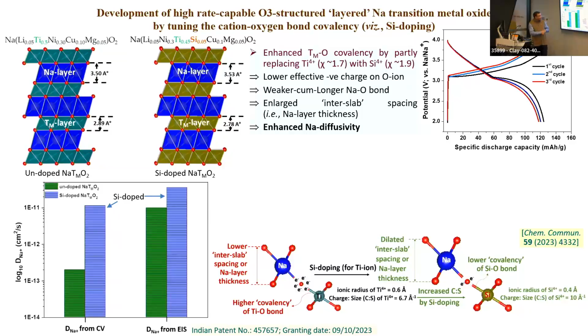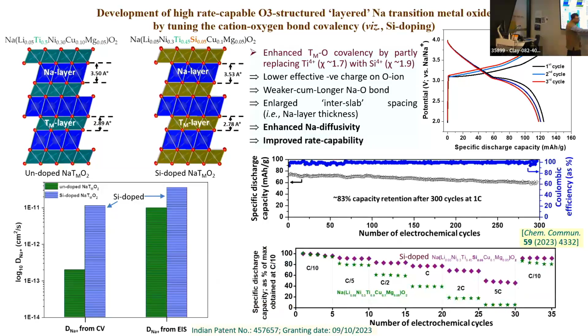So again, going back a little. Now this on the left hand side is the composition which was absolutely water stable, using which I had shown the aqueous process cathode. It was perfectly water stable. But then the rate capability was not that great, understandably. So we tweaked it a little bit. In place of titanium, we replaced a little bit of titanium, just a little bit, with silicon. Both 4+, but silicon has a greater charge to size ratio, greater covalency, which made my transition metal oxygen bond a little less ionic compared to this one. It also dilated my sodium interslab spacing just a little bit, so that it did not negatively affect the air water stability, but it improved the rate capability significantly by improving the sodium diffusivity.